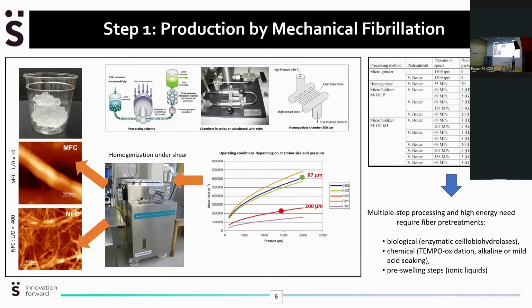Of course, it's a very energy-intensive process because we need to break the hydrogen bonding in the cellulose structure. So it's not the most energy-efficient process. As you see here, high amounts of energy consumption are needed. So at the moment, we are also involved in projects where this fibrillation process can be enhanced, for example, through pre-swelling of the cellulose fibers.